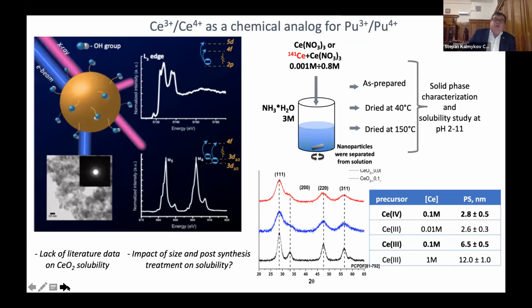So the last example that I would like to show, maybe 2 minutes more, is Ce(III), Ce(IV). Cerium itself is a very, very important material. It's used in photocatalysis, pigments. It's even used in medicine as an antioxidant. And the important thing that we were looking for is, again, an analog for plutonium(III), plutonium(IV). When we have plutonium dioxide precipitate, for example, if there is some presence of Ce(III) on the surface, if we go down to nanometer-sized particles, what is the chemistry behind their higher reactivity and this antioxidant activity?